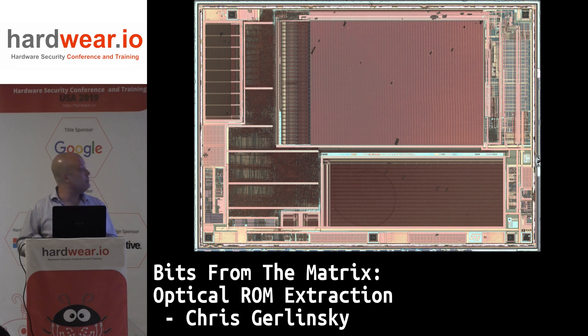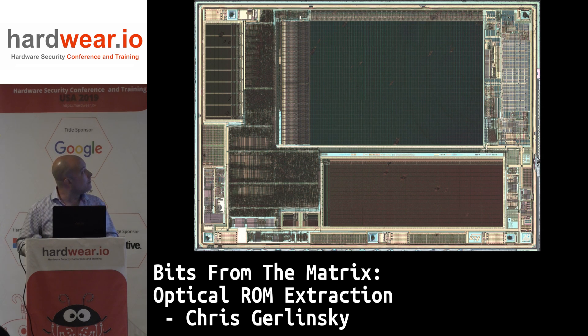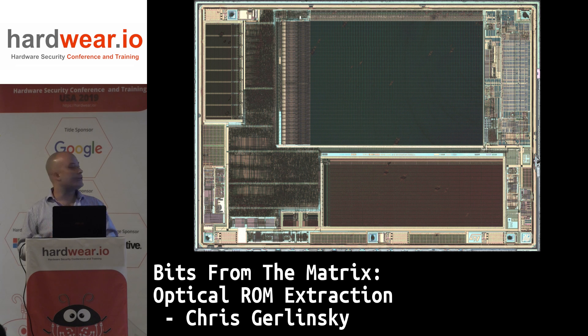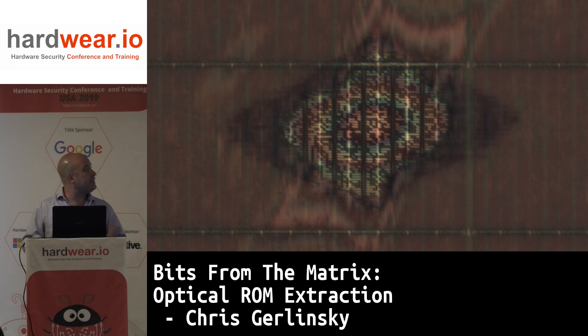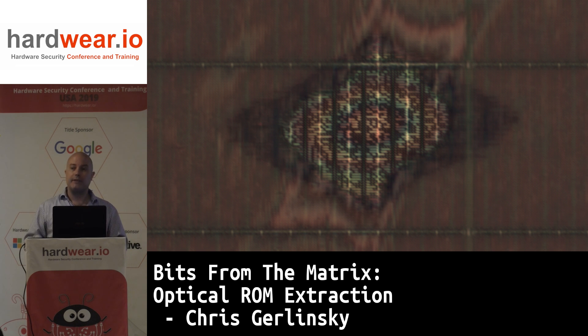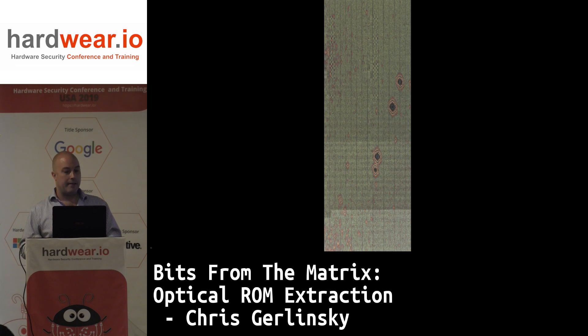After this I put the chip back in HF since we can't see any bits yet — they're still down lower. After another couple of minutes in hydrofluoric acid we've stripped away another layer. There are still more metal layers and inside the ROM area a few spots where the acid has pooled and etched a bit deeper, so the de-layering isn't perfectly level. The deeper you go with wet etching the more difficult it is to keep it perfectly level — a solution is to combine wet etching and polishing to keep it planar. Where it's etched deeper into the next layer, we can start to see some of the bits — the bits encoded on the next metal layer. After another dip in HF to remove the remaining layer, all the bits will be exposed.